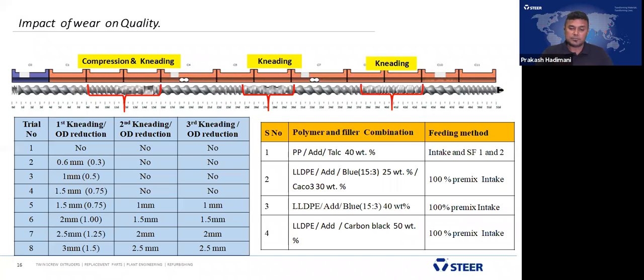In the impact of wear on quality, we have selected 3 zones. One, you see here, was the compression and kneading section. The second zone we call kneading, and the third zone is again one more kneading section. In this DOE, we selected first kneading, second kneading and third kneading. In the first combination of this DOE, first kneading has no OD reduction, followed by second and third. When you put on the screw with no OD reduction, as it is, for a 40 millimeter extruder at 1200 RPM, the screw diameter is 39.7. Per side, the screw to barrel clearance is 0.15. That is the actual. There, no OD reduction, we started and demonstrated.